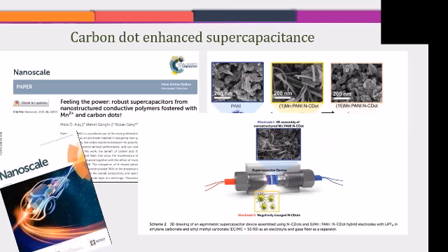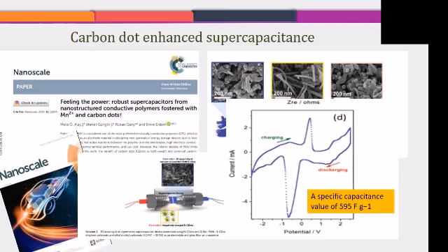We got huge efficiency with that. We got a specific capacitance of 595 farad per gram. So this was huge outcome. Now we are continuing with these studies to have smart supercapacitor with the Dr. Erdem.